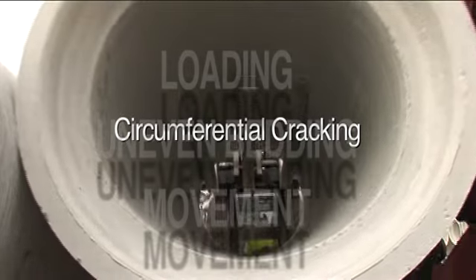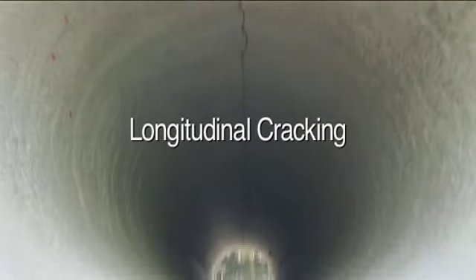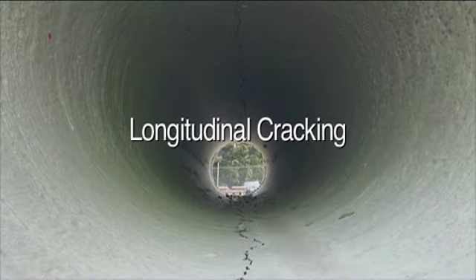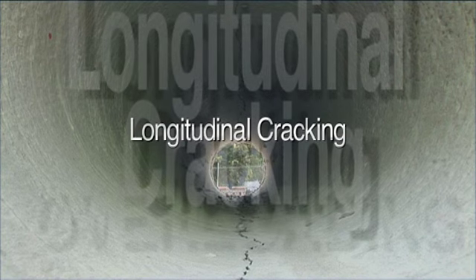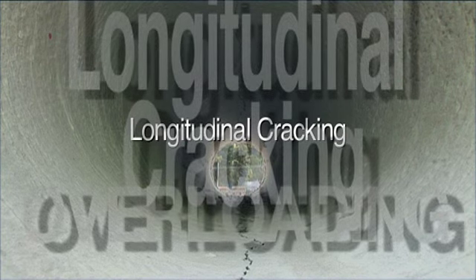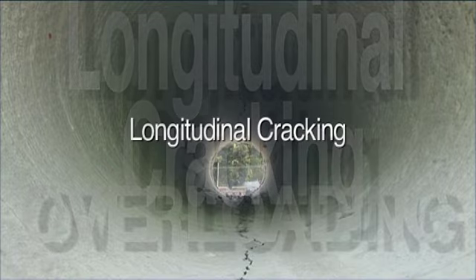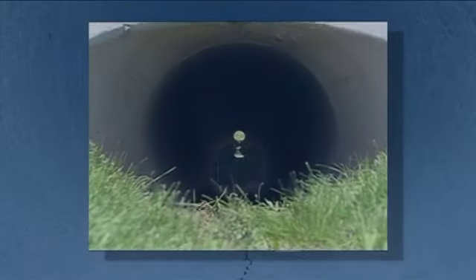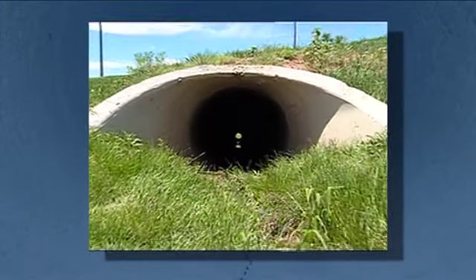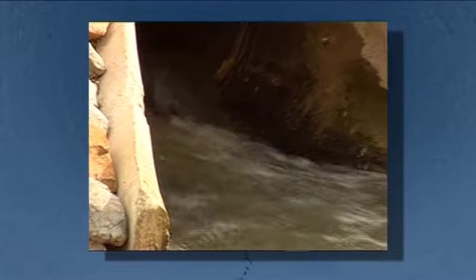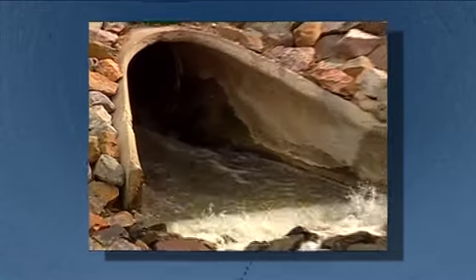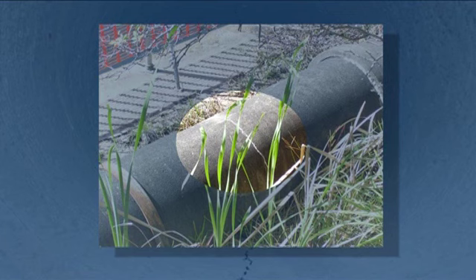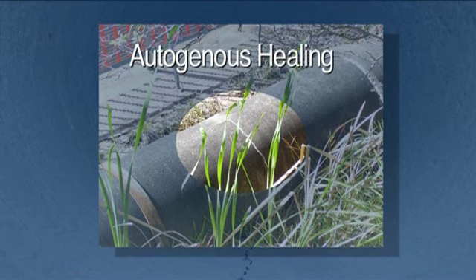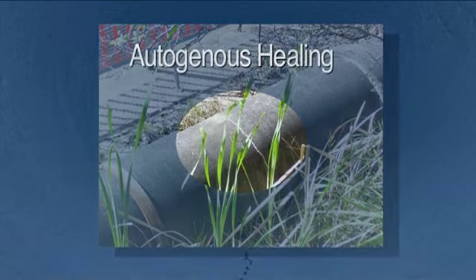Circumferential cracking can occur during installation due to loading, uneven bedding, or movement from settlement. Longitudinal cracking, however, is due to overloading and requires detailed review to establish the cause to ensure the structural adequacy is not jeopardised. As steel-reinforced concrete pipes are generally buried underground and carry water, the cement continues to hydrate. As a result, many cracks are able to heal themselves due to a phenomenon known as autogenous healing.